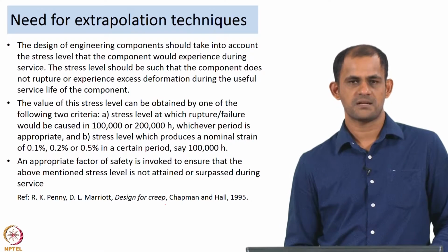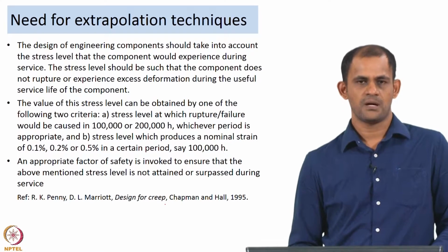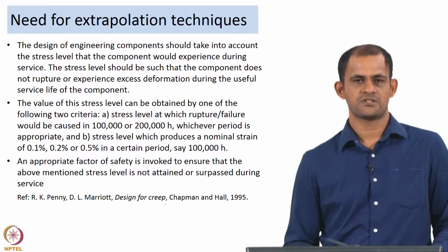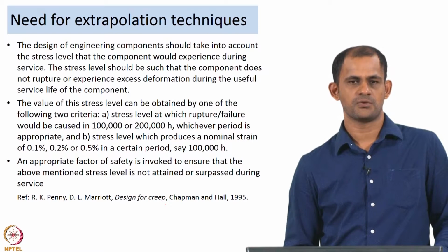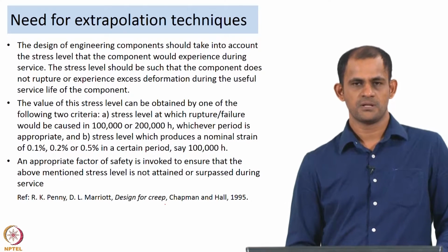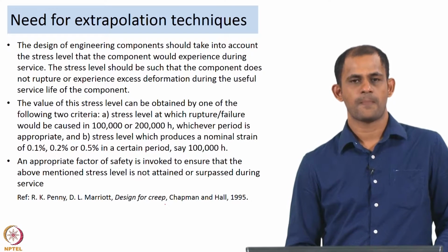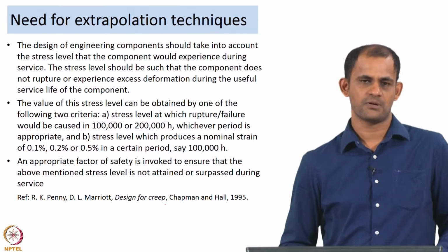Well, the value of the stress level can be obtained by one of the following two criteria. These criteria have been listed down by people who regularly do this kind of work. The first is the stress level should be such that the rupture or failure, in case you are allowing your component to go up to rupture, then the stress level should be such that your rupture life should be at least 1 lakh or 2 lakh hours of operation. So, the stress level at which the rupture or failure would be caused in 100,000 or 200,000 hours, whichever period is appropriate or required for your application.